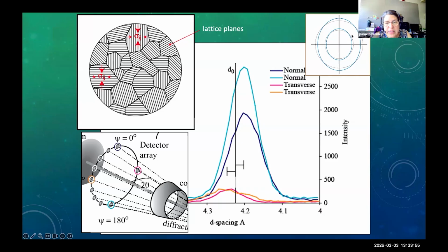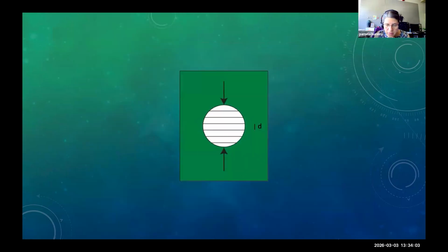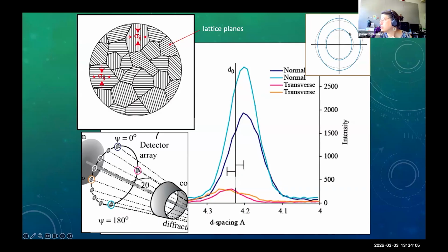But basically what we see is that the D-spacings, I'm looking at my screen, it's chopped off at the top, but you guys, whoops, no. Okay, you see the whole thing. So the D-spacings get shorter. The blue is the after, and the little dashed lines are the starting point. So these are little Debye rings. So basically your circular rings turn into an ellipse, okay?